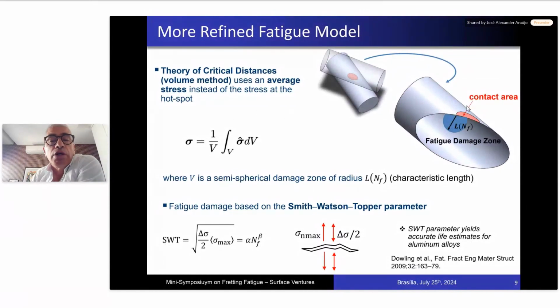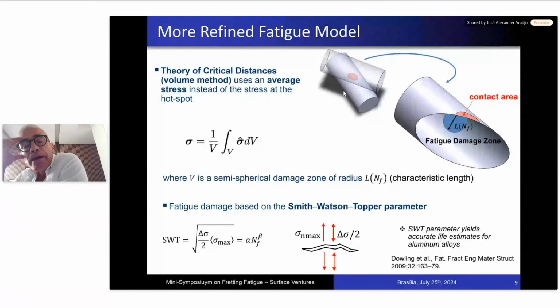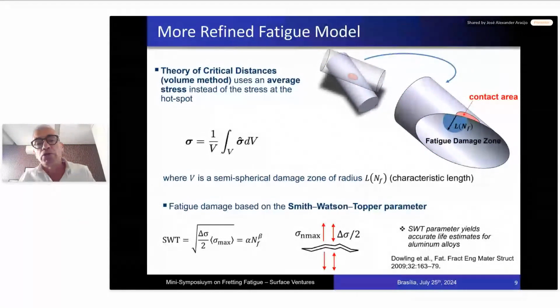So what we do to consider that is to use the theory of critical distance. In this case, we are going to use the volume method, and when we have the contact of the wires, we will find the most severe loaded point on the elliptical surface that will be formed, and then in that point we will build this process zone and integrate the stresses within this volume to obtain an average stress tensor, within this blue region. So that's the strategy that we are going to use to try to estimate the life for the contact of these two wires.